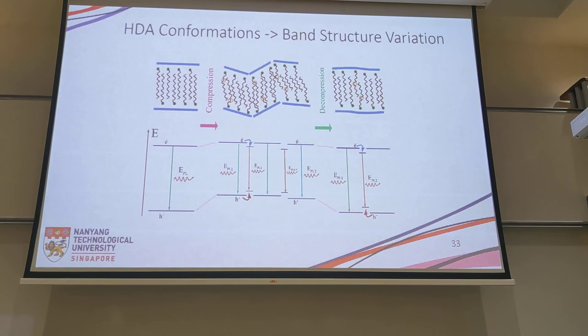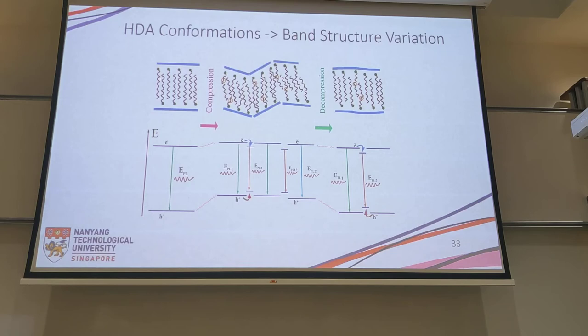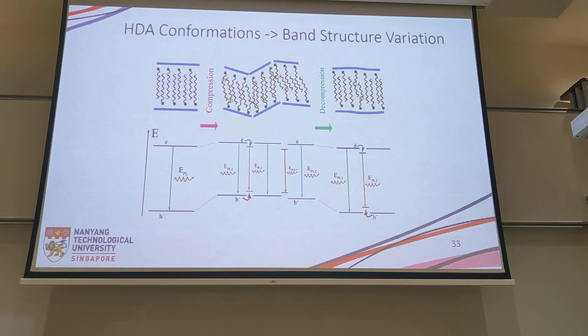The next slide is mainly a hypothesis explaining why this happens. The schematic shows that at room temperature before compression, we have straight HDA chains. When compression happens, the very soft organic substructure has many ways to respond to pressure — for example, bending of the chains in different positions in different parts of the structure. Different bending configurations cause different distortions in the inorganic layer, resulting in different band structures and thus different PL positions and optical absorption across the crystal, creating the observed domains.